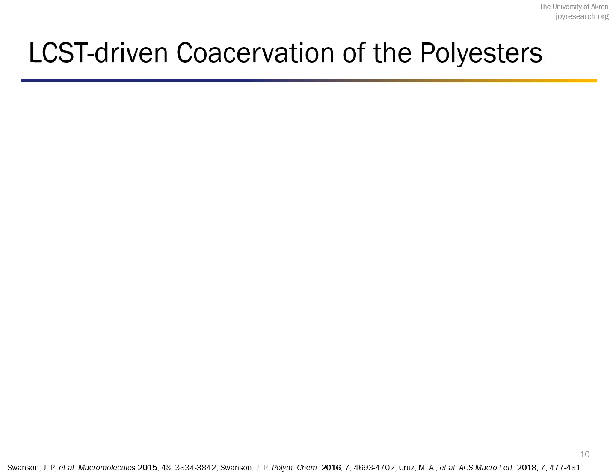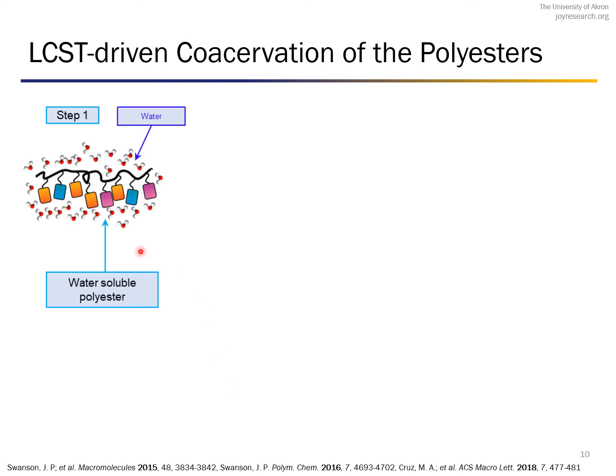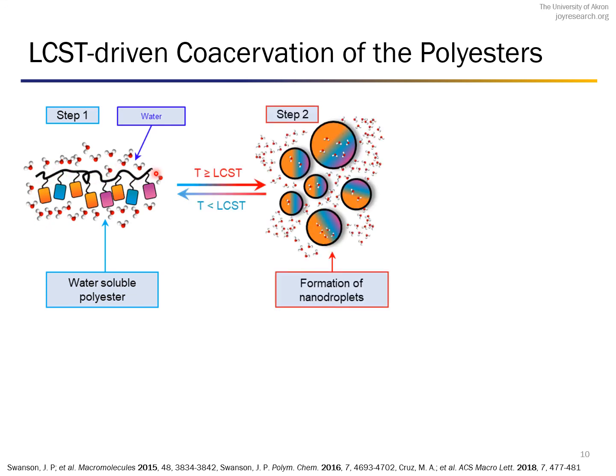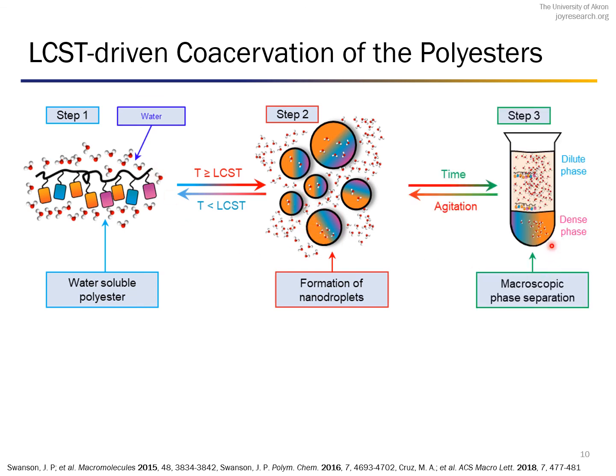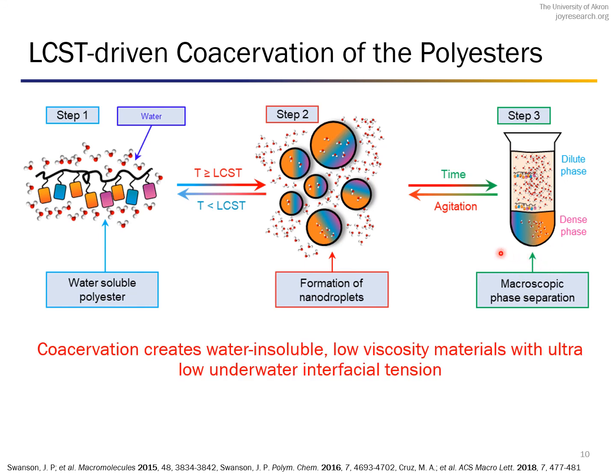In my study, we have created a proto-elastin-like polyester which has LCST-driven coacervation. These polymers dissolve at temperatures below the LCST, and above the LCST they form nano droplets which later condense to form this dense phase. And this condensed dense phase is water insoluble, and at the same time it has low viscosity and ultra low interfacial tension. All these properties allow it to spread in underwater conditions.